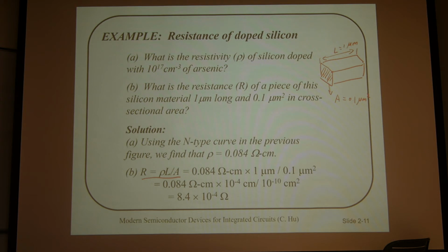So that's why sometimes if we dope the silicon heavily, this one is not even heavily doped, 10 to the power 17. It's the kind of high doping, but not the very high, because you can do up to like 5 times 10 to the power 18. So if you do this heavy doping, then you can use this as interconnect, local interconnect, as we discussed before.